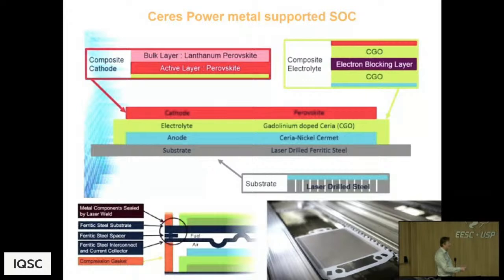And you can see that the support material has been made with a bit more sophistication in terms of the sealing arrangements and the flow distribution arrangements. A porous ferritic steel substrate, a ceria nickel cermet as the anode, a gadolinium doped ceria. Importantly, for anyone interested in using gadolinium doped ceria, it's a difficult electrolyte material to use.